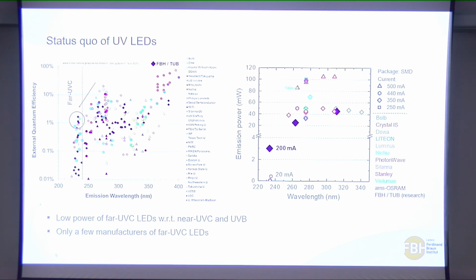And you see that when you're in the UVA region, you have nearly 80% efficiencies, you have very efficient devices, but as you go to shorter wavelengths, the efficiency drops very drastically. And if you go to the far-UVC wavelength, it drops even more. So you have around 1% external quantum efficiency. So most of the energy that you put into your system is going to be converted into heat, and that's why you have this big heating problem when you have far-UVC or UVC LEDs.